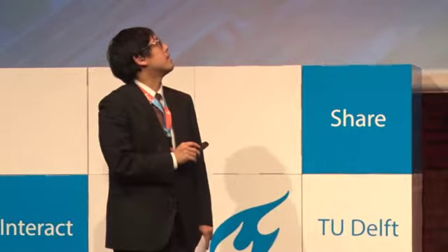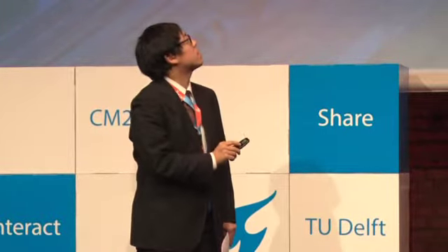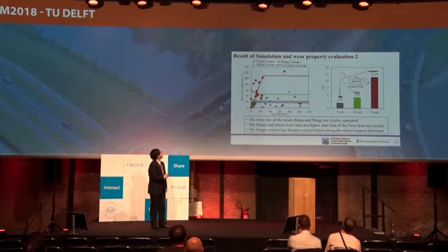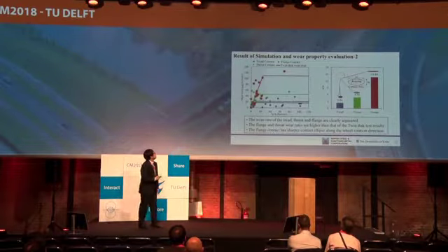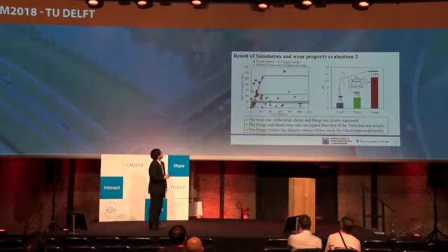And this figure shows the relationship between T gamma by A and wear rate. The red points are flange contact, the green points are throat contact, and the blue points are tread contact, and the black line is the reference twin disc wear map.